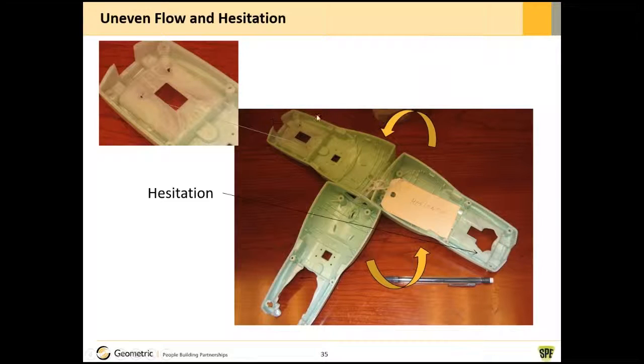Here we have a part that has a thick area surrounding a thin area. So what happens is the plastic flows into the thick area, path of least resistance, and then it realizes, oops, I have to fill this area too. By this time the flow front temperature has come down rapidly. It's not flowing. The pressure is reduced dramatically. So it doesn't have enough temperature, enough oomph in the pressure to fill this part. You're going to have a resultant void in the part.